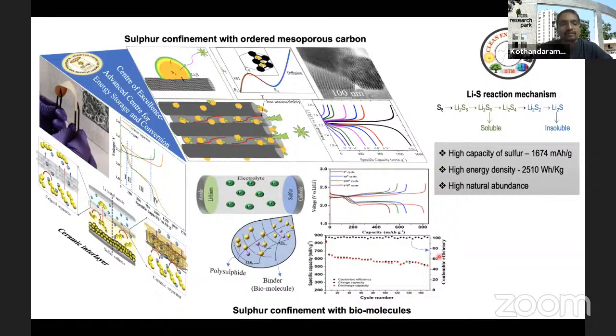Another approach that we have is not letting this sulfur go into solution, but converting it directly into an insoluble form of sulfur, Li2S2 or Li2S. For that we have used some confinement chemistry. Therefore, you don't see two plateaus here. There's only a single plateau. Moreover, the polarization, that is the voltage difference between the charge and discharge curves, is also very minimal here. So the energy loss because of storing and retrieving of these charges is very minimal in this case.